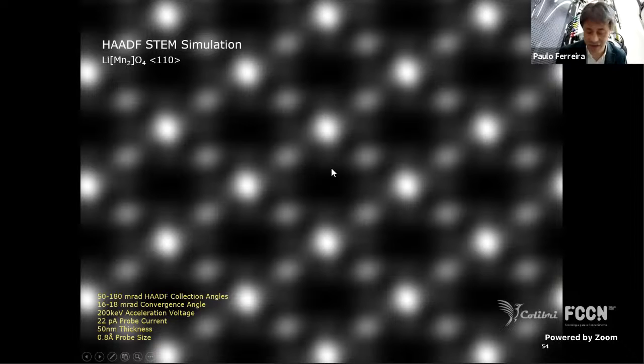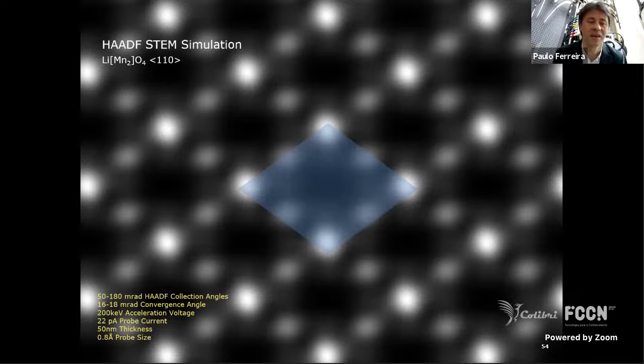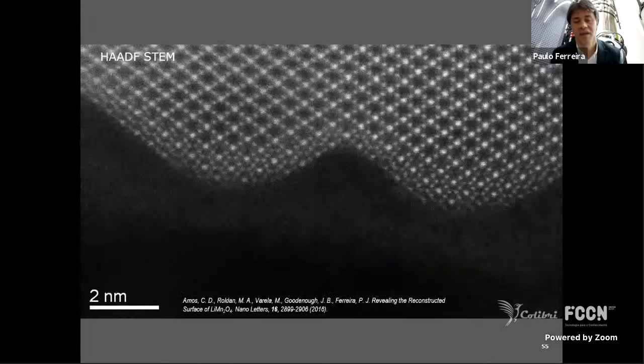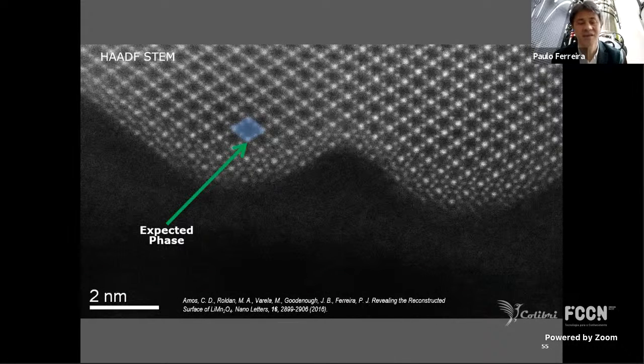Just look through that direction, and you see this diamond. With this technique, what you see is the manganese atoms. You cannot see the lithium and the oxygen, but you can see that the manganese forms these diamonds here. So then we can go to the microscope, and as shown here, this is a real image from the microscope, and as you expect, inside is exactly this diamond where you see the manganese atoms. But you see that the surface is rather different.